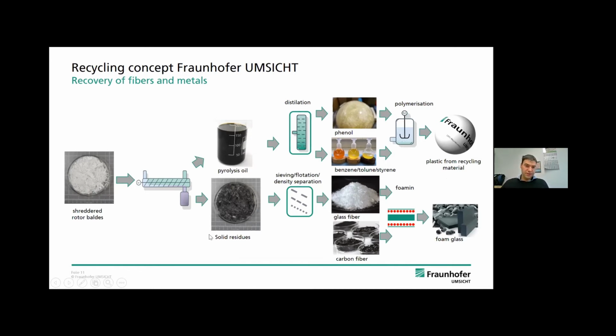But we are also working with the solid material. In the case of fiber reinforced plastics, we do some mechanical physical separation processes like sieving, flotation, or density separation, where we can end up with, for example, glass fiber or carbon fibers. And in this case, we are using these fibers for a foaming process to produce foam glass.